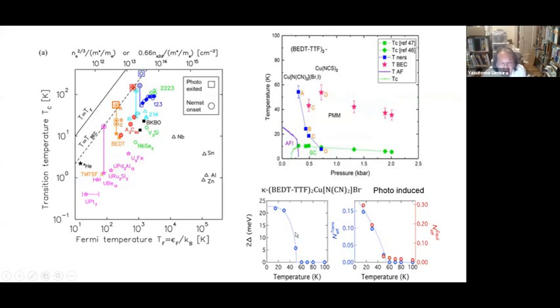Okay. Now, probably the most interesting thing is to see what is happening in the case of the cuprates. So this is the phase diagram of the cuprates. And firstly, I show the Nernst effect onset temperature and the diamagnetism onset temperature here. And this is the actual TC. And this is T star, which would probably mean pair formation or boson formation. And obviously, first of all, this Nernst effect onset is much, much lower in temperature than this T star. Okay, that's a very important thing to realize first.